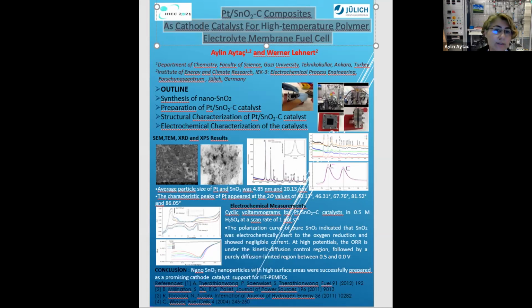Hi, dear participants. Now I would like to give some very short information about our high temperature PEM fuel cell study titled tin oxide carbon composite supported platinum as a cathode catalyst for high temperature polymer electrolyte membrane fuel cell. As you know, some of you, high temperature PEM fuel cells have some advantages. For example, high tolerance to carbon monoxide, no humidification necessary, simple water management, compact cooling system, possible usage of the waste heat. One of the major problems is the electrode materials degradation in the low pH and high temperature environment. The continuous degradation of the fuel cell performance is mainly attributed to carbon-supported corrosion and the degradation of